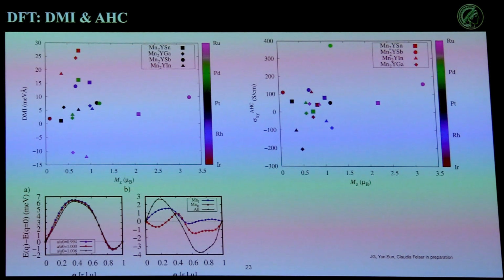Another thing we did is we did many more compounds, but we just show a few here. We change the Z element, the X element, the Y element, and we look at the DMI and anomalous Hall effect. These are somewhat correlated because the anomalous Hall effect is a spin-orbit effect also, but it's in momentum space. The DMI will tell you the size of your skyrmions, which will also tell you the size of your effective transport. What you really see is that it goes up when you put iridium in these cases or you put ruthenium in. This is just because you shift the Fermi energy down to that point where the Jahn-Teller distortion causes this. As a function of strain, the DMI doesn't change, and you can see you also have DMI on all the lattices, but the strongest is always close to interactions.